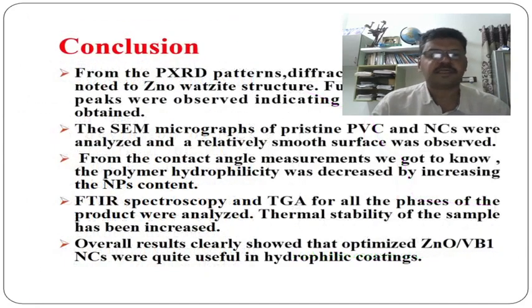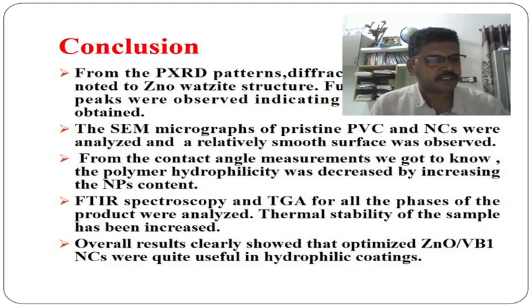Knowing this, I am going to give the conclusions about my topic. The ZnO, VB1, PVC and NCs were prepared by a user-friendly solution casting route and characterized by various spectroscopic techniques. The hydrophilicity decreases with increasing ZnO, vitamin B1 content of the PVC matrix. The TGA result shows an increase in thermal stability upon ZnO B1 content. Overall results clearly show that optimized ZnO B1 and NCs are quite useful for hydrophilic coating.